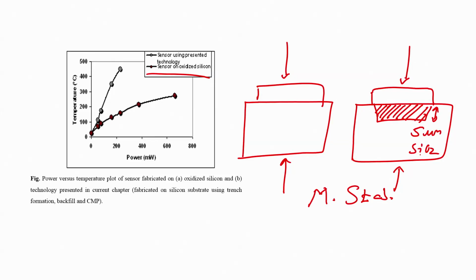By doing so, we are creating a thermal insulator, and that is why the heat loss from the back side of the wafer will be reduced, and thus the difference in the temperature that we get for the same amount of power is tremendous. You can see here, if I say about 200 milliwatt, we are achieving 450 degree centigrade, while for this particular substrate we are around 150 degree centigrade. You see a difference of 300 degree centigrade, right.